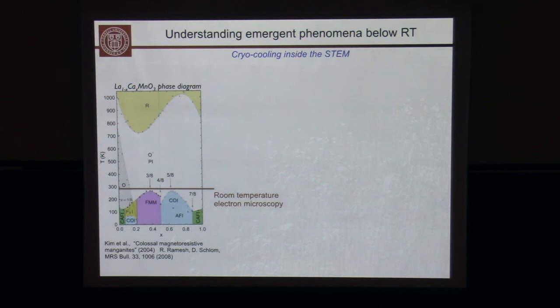All the work that I've shown you so far was done at room temperature. And the reason why we've performed all these measurements at room temperature is because getting stable imaging and stable spectroscopy at, let's say, liquid nitrogen temperature is very, very difficult. And people have tried, but atomic resolution that allows you to measure with high precision has not been obtained before.